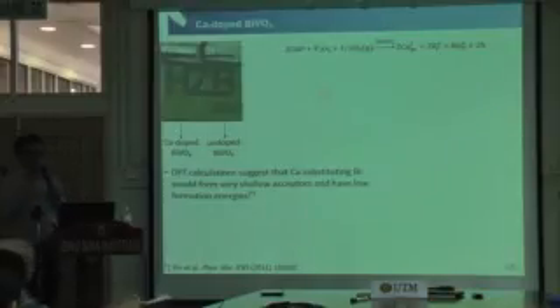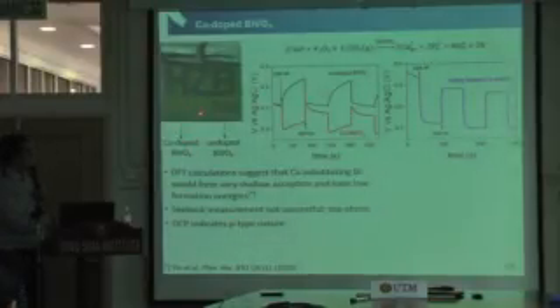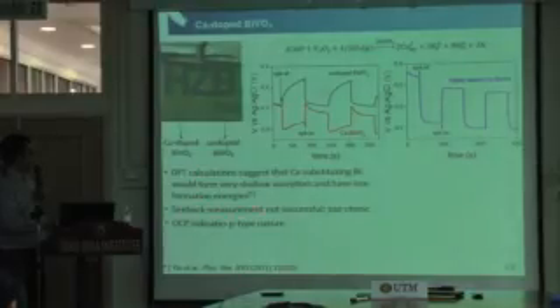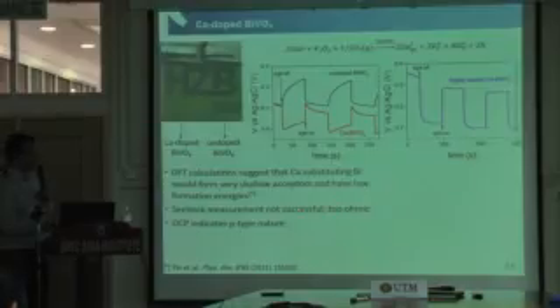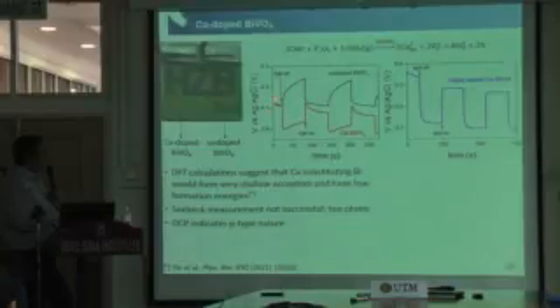And the idea is that if you have a p-type and an n-type, the degree of control that you have on the electronic nature of the materials is becoming so wide that you can think of other heterostructures or homostructures that you may be able to build with this material. So we did that. We tried to make calcium doped bismuth vanadate. It looks really similar. But we are having trouble trying to measure Seebeck because the films are too ohmic, and Hall effect, same way.